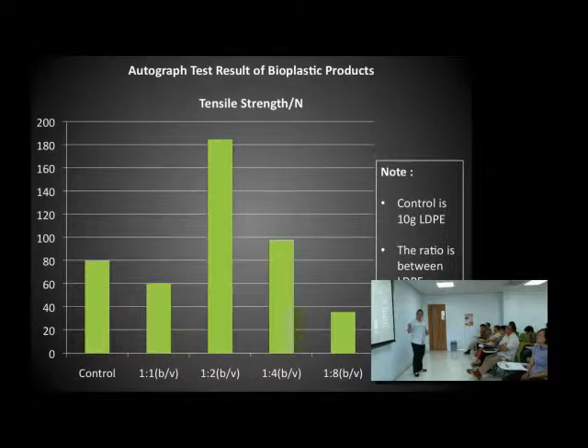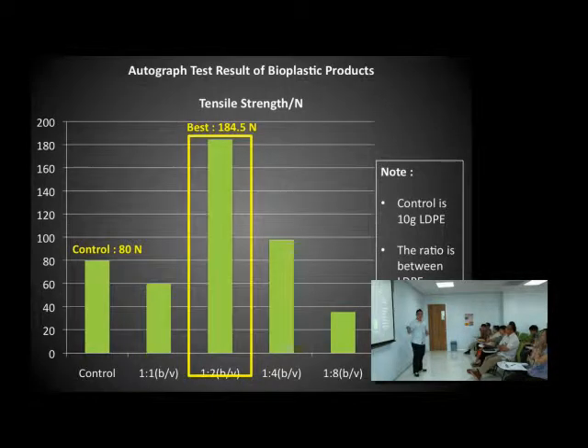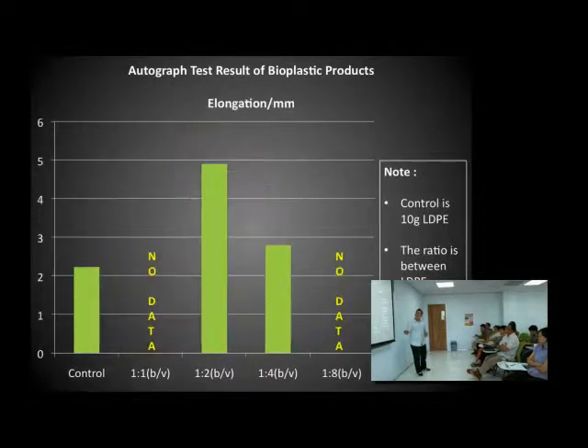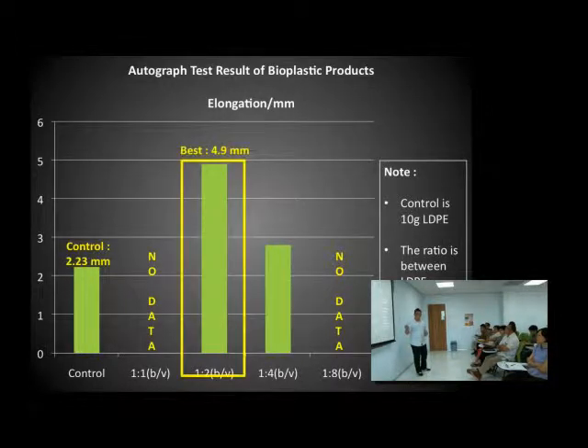Well, here's the result of the autograph test for bioplastic products. For the tensile strength, we can see that 1:2 provides the best result. It is 184.5 Newton, while the control is only 80 Newton. And for the elongation, we can see that 1:2 still provides the best result. It is 4.9 millimeters, while the control is only 2.23 millimeters.